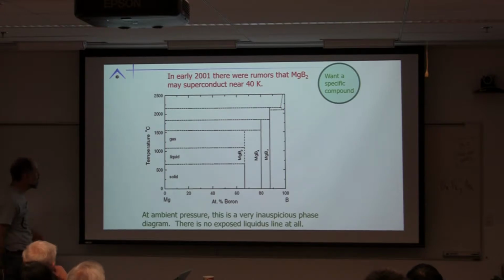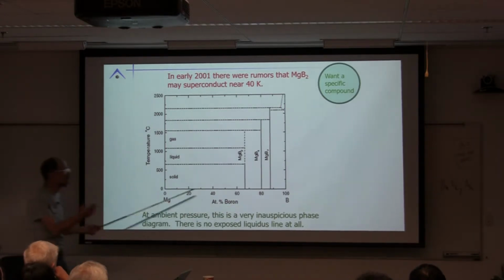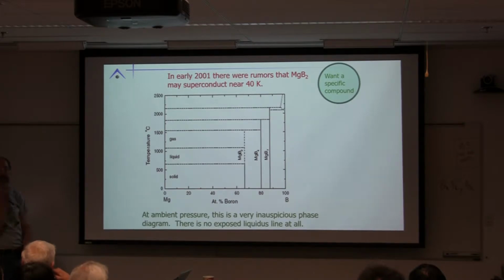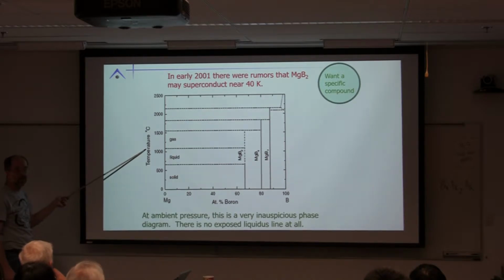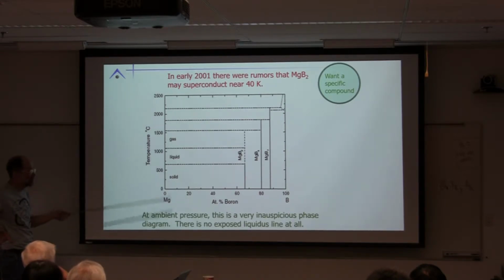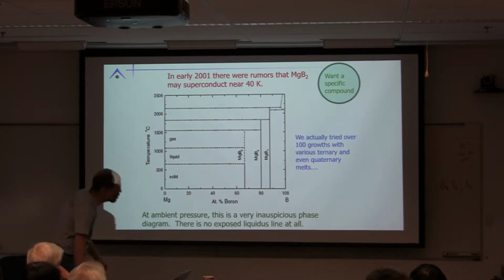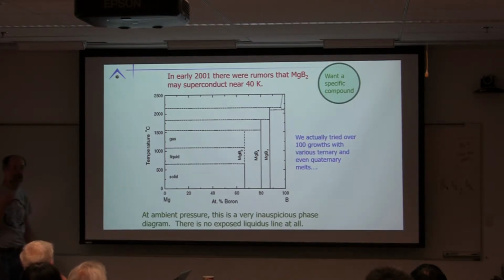So, quick, look at the binary phase diagram. Here's magnesium, here's boron. Find the liquidus line, we're good. There is no liquidus line. Okay? This is a highly inauspicious phase diagram for solution growth. And despite many attempts to grow this out of binaries, ternaries, quaternaries, I used almost a kilo of platinum trying to grow this. Now, I gave it back. Okay? We recycle our platinum. You don't need to dig through my trash. But it was not something we could grow as single crystals, okay, at ambient pressure, okay? Because there is no liquidus.